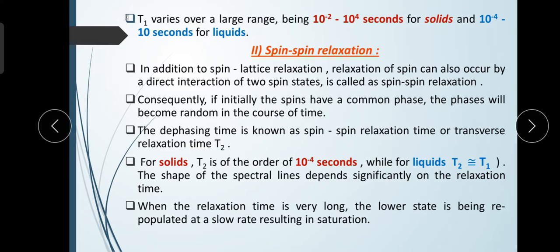Again, same as the spin lattice relaxation time, T2 has different values for different materials. That is, for solids T2 is of the order of 10 to the power minus 4 second, while for liquids T2 is nearly equal to T1. That means if we consider a solid material, the spin relaxation time T2 is in the order of 10 to the power minus 4 second, but for liquids the spin lattice relaxation time T1 and the spin relaxation time T2 both have nearly the same values.